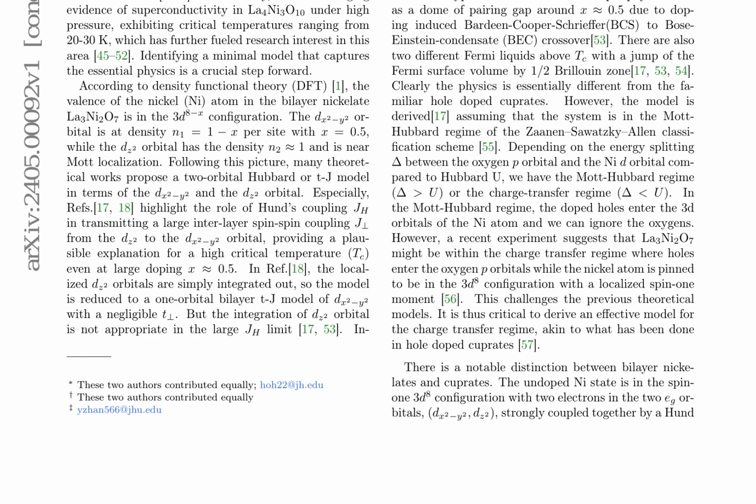The derivation of the Type II t-J model from the charge transfer Hamiltonian is a pivotal step in understanding the spin exchange interactions between two nickel atoms. This process involves dividing the charge transfer Hamiltonian into a kinetic part, V equals H_dp, and a remaining part, H0 equals H minus V. The J-perpendicular terms are then derived, with the example of J-perp SD being demonstrated. Due to the SU(2) symmetry of the Hamiltonian, generalization to J-perp SS and J-perp DD is straightforward.